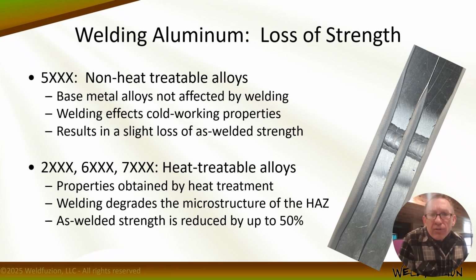Now, because a loss of strength occurs in the base metal, filler metal selection really doesn't come into play here, right? That's more based on other factors. For example, 6061 can be successfully welded using either 4043 or 5356 filler metals. Both have higher tensile strength than 24,000 psi, and thus the base metal would fail long before the filler in a properly welded alloy.